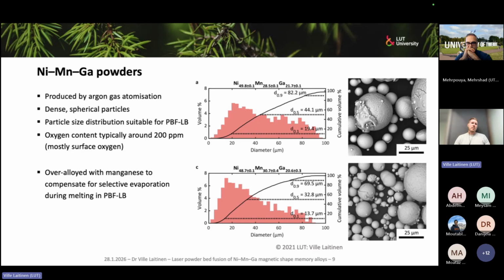Then also an advantage, because it happens in an inert atmosphere, is that we typically have a very low oxygen amount in the powder itself. What we have been measuring from our powders is typically in the range of 200 ppm. Of course, this can significantly degrade if you are recycling your powder, so you can start accumulating quite substantial amounts of oxygen, and that's critical from the point of view of making functional material: you might need to keep a track of how much oxygen you are putting into your powder.